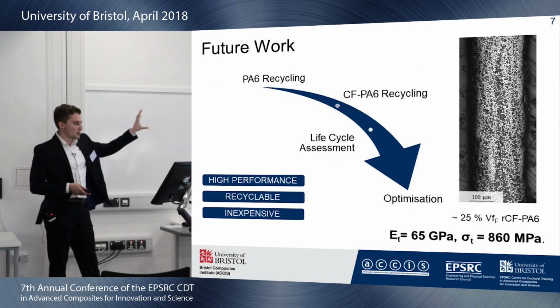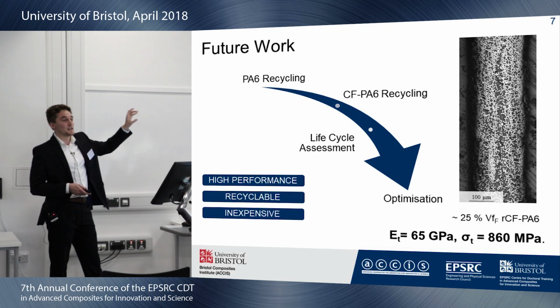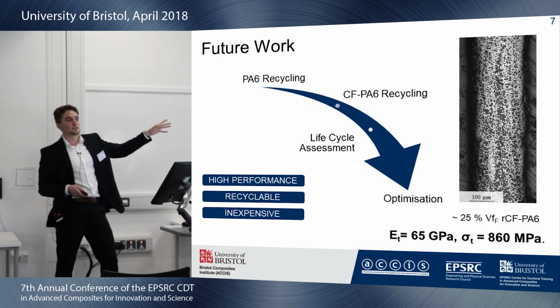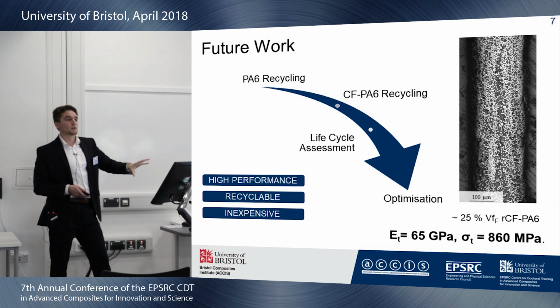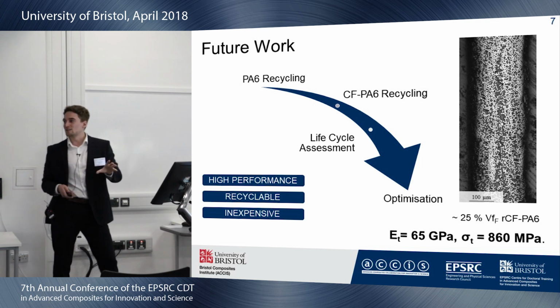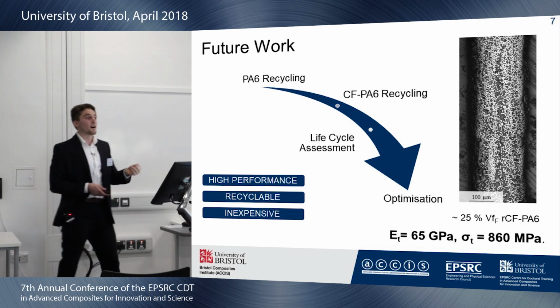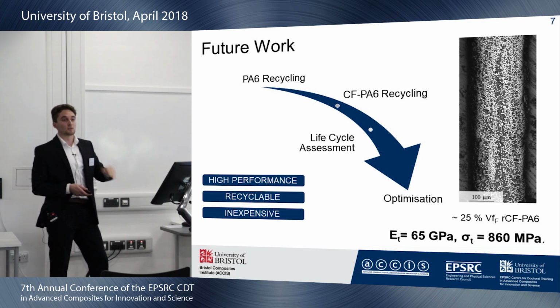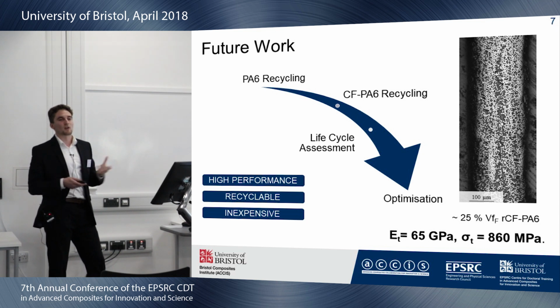So I've created a high-performance, recyclable, inexpensive material and process, but now I want to use an industrially applicable matrix like nylon 6. I've made some specimens. I've got a stiffness of 65 gigapascals and a strength of 860. So that started off well, and now I want to recycle those and see if I can keep those properties throughout the recycling. I want to do a life cycle assessment to evaluate and quantify how much of a burden I can decrease by using my recycled components. And also I'd like to optimize things like volume fraction and adhesion further down the line.